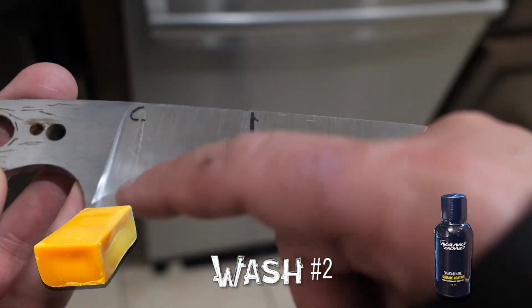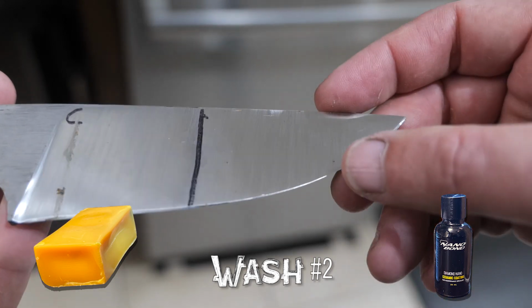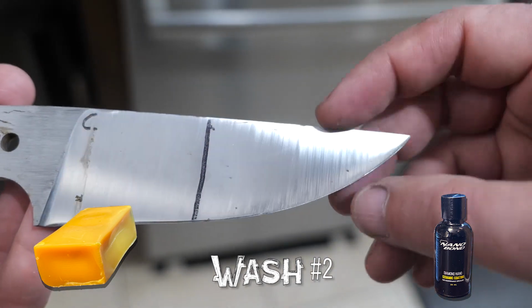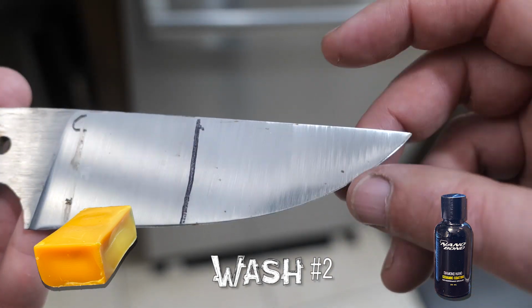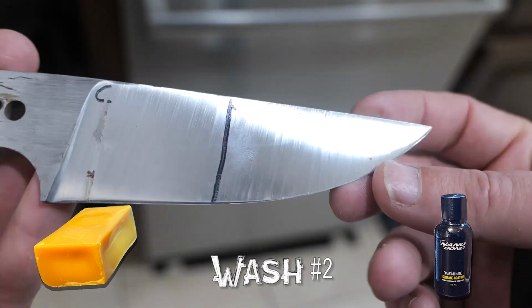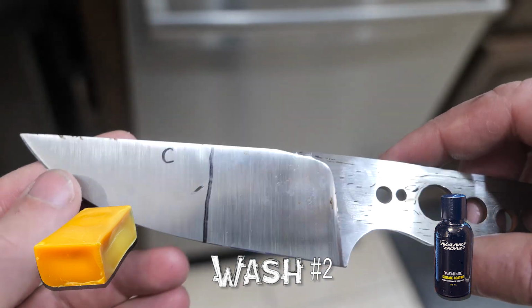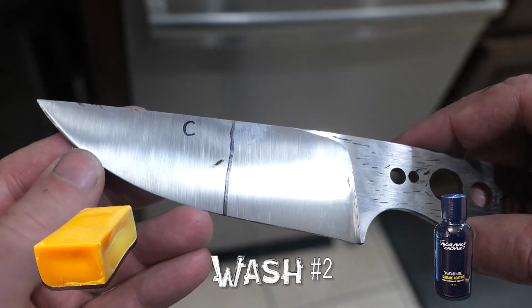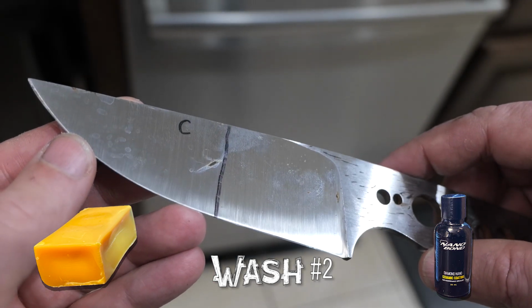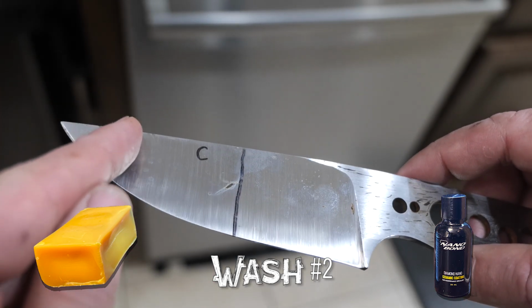To me, it looks like both coatings survived the first wash and are still active during the second wash. There's only a few more additional spots here, mostly around the tip of the knife, which is what we saw in the past. I'm going to give the edge here to the Carnauba wax, though, which is hard to believe. I would have thought that the Carnauba wax would have washed off. These are probably creeping. How well do these knives stand up to a little bit of use?